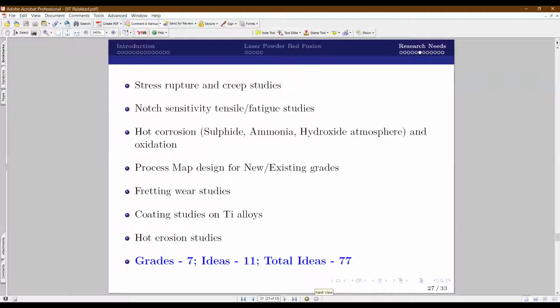As these alloys are used up to 500 degrees, of course, creep and stress fracture are very important. So data is not available. I urge all the academicians to focus their energy on developing this data. And most of the aerospace components are complex in shape, and by virtue of the process nature, it is meant for complex shapes. So conventional smooth samples data may not be that relevant for the complex shapes.